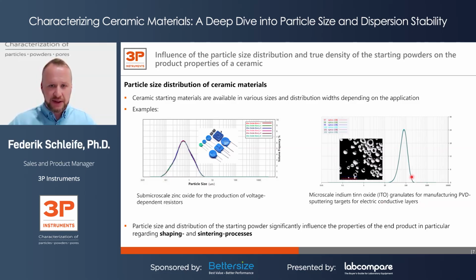So you see here, the size is narrowly distributed, normally distributed, shortly below 100 micrometer. So there's not really a typical rule to say all ceramic raw materials need to be below 1 micrometer or need to be around 100 micrometer. It really depends on the application itself.